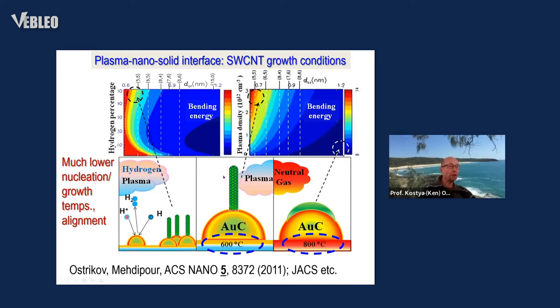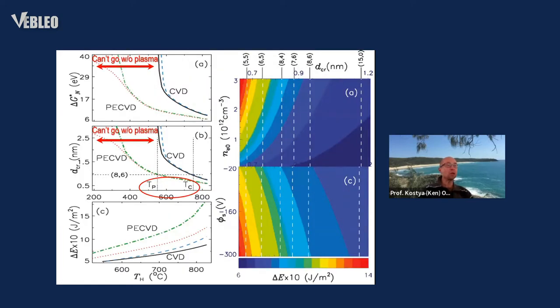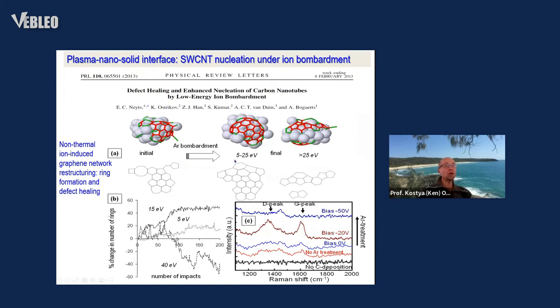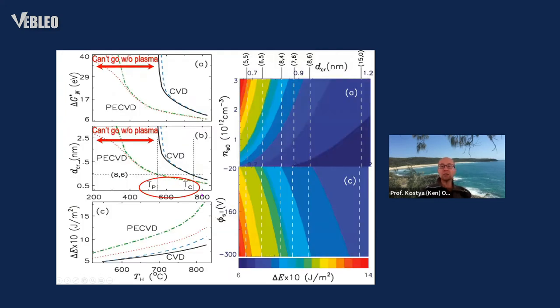The very interesting point is that when the carbon nanotubes grow in plasma, the growth becomes possible at temperatures that are significantly lower than in normal thermochemical deposition processes. Very often, by the order of a couple of hundred and sometimes even more degrees lower than using other typically thermal processes. In this highlighted example from one of our earlier works, we can see that a selected single-walled carbon nanotube with (8,6) chirality nucleates in a plasma at almost 200 degrees temperature lower than in the normal thermal CVD. And this owes to the increased bending energy of the graphene initial layer that bends and extends, also assisted by the electric field of the plasma to form the established carbon nanotube.